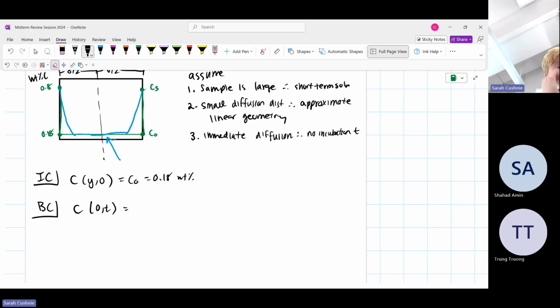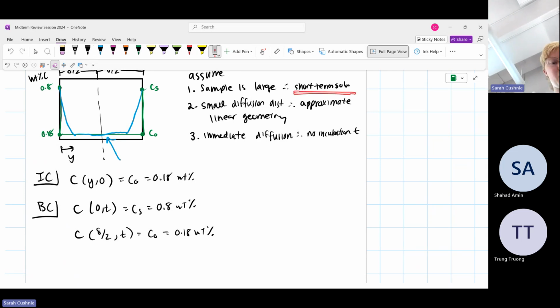So no matter what time, at a distance of 0, call this y, we're going to have the same concentration, CS, at the surface, which is 0.8 weight%. And the concentration at distance delta over 2 and any time t is equal to C0, which is 0.18 weight%. What we're saying here is, again, that we're using a short-term solution. So no matter how long you keep it in the furnace, within reason, we're never going to reach that long-term solution. We're going to keep that initial concentration in the middle so that we can use this short-term solution.